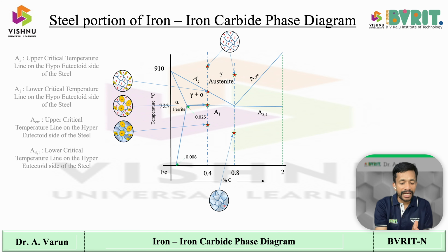So it will start by forming a plate-like structure. That is a cementite plate, and then on either side it will have a ferrite structure. Then again cementite plate, and then ferrite, cementite, ferrite. So like that, you have alternate layers of ferrite and cementite. It's basically a laminar structure, a fingerprint-like structure, which represents a pearlite reaction. So that's why you can see each grain is hatched, and its orientation will differ from one grain to the other grain. So that is the pearlite formation.